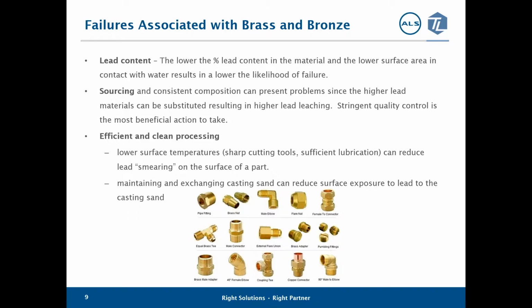There are a few things manufacturers can do to lower lead extraction from lead alloys. The first is the one I had already mentioned, and that is to reduce lead content in metal alloys. The lower the percent lead content in the material and the lower surface area of the lead-containing material in contact with water results in lower amounts of lead in drinking water.